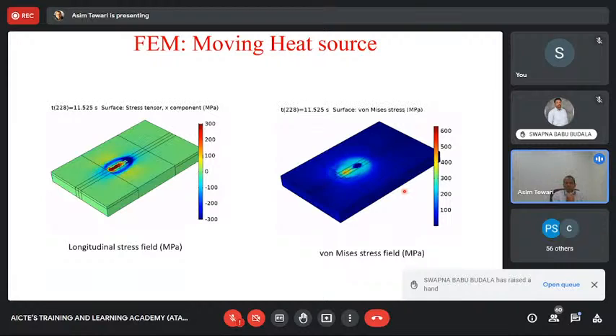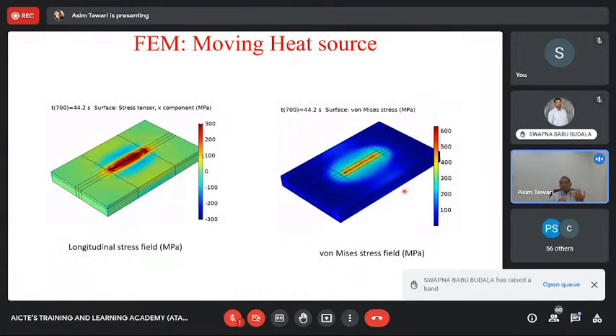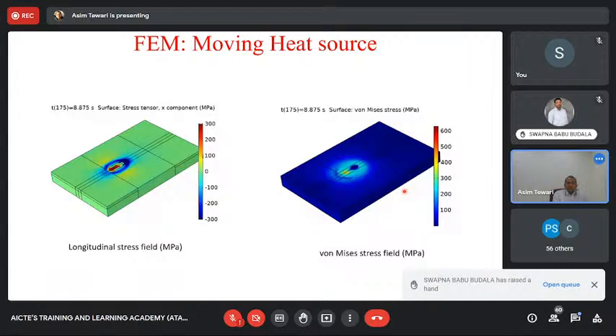Now, this is essentially a simulation of a single moving heat source, a single streak of heat. In this case, to validate this, we used welding. Why welding? Because welding is a well-known process. You can very nicely instrument it, and a single bead of addition of weld material is the same as additive manufacturing. If you do multiple of them, it becomes your additive manufacturing.